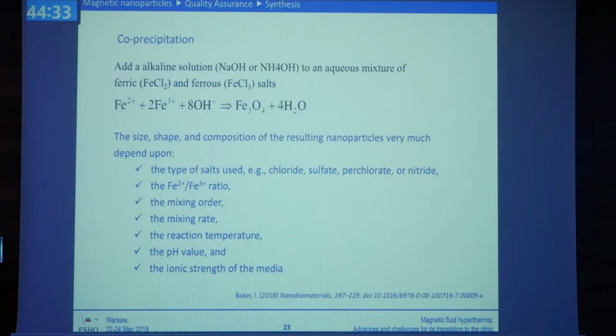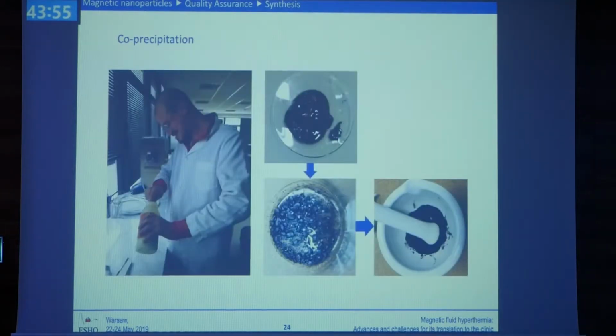Another technique that we use in our lab is coprecipitation, where you can use different mixtures of ferric and ferrous salts of iron, and then you have an alkaline solution again, and you mix them together. But depending on various factors, like if you put first ferric instead of ferrous and so on, even the mixing order of the different materials can lead to different nanoparticle sizes and to different dispersions. But anyway, this is what we do now, and we have tried several ways of mixing, of keeping the temperature and so on. And now we end up with very good nanoparticles.